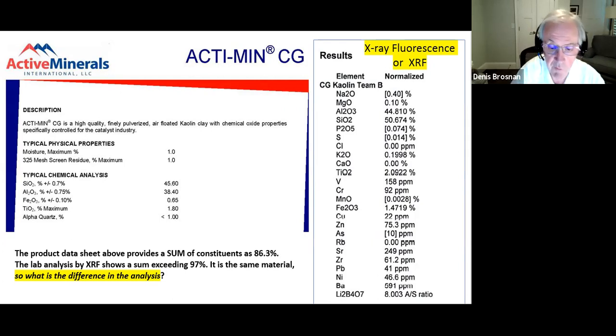Importantly here is alpha quartz. That's crystalline silica, SiO2, less than 1%. That really affects the firing process, and we'll get to it later on. Now, if you add all those numbers up on the product data sheet, you get about 86.3%. Well, where's the rest of this?